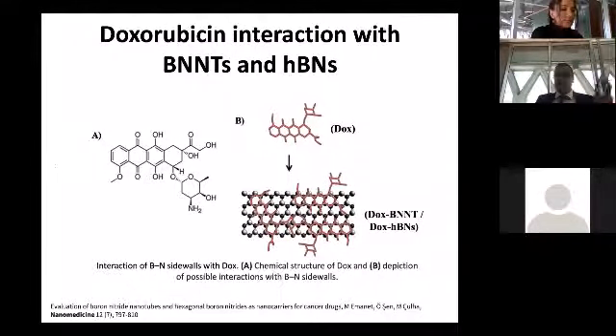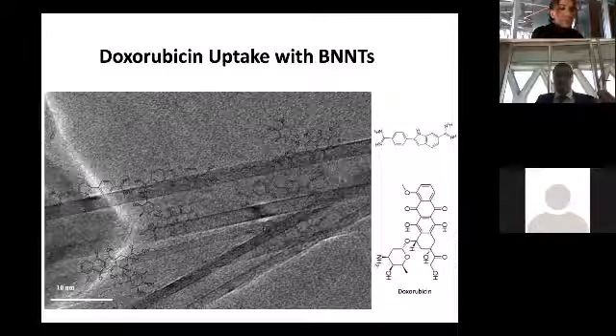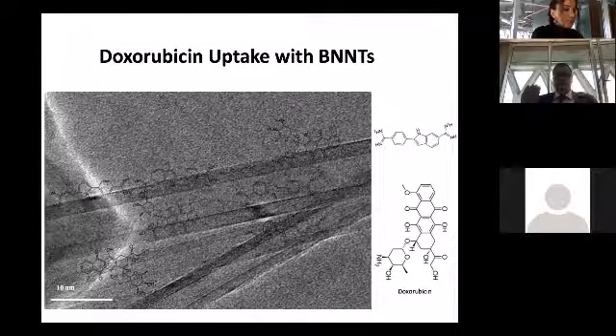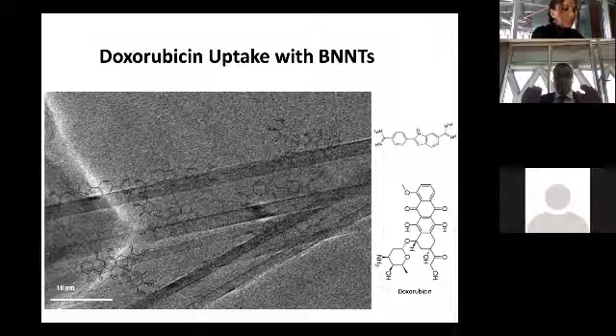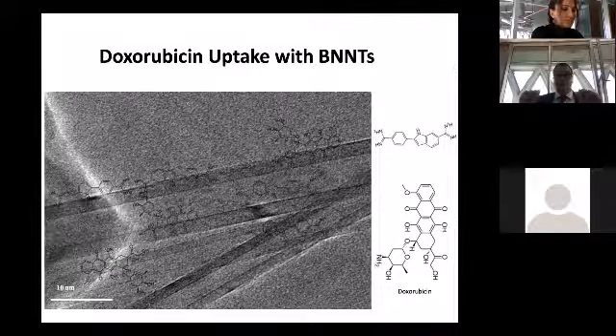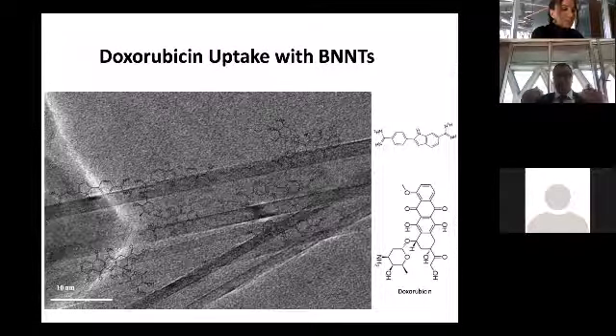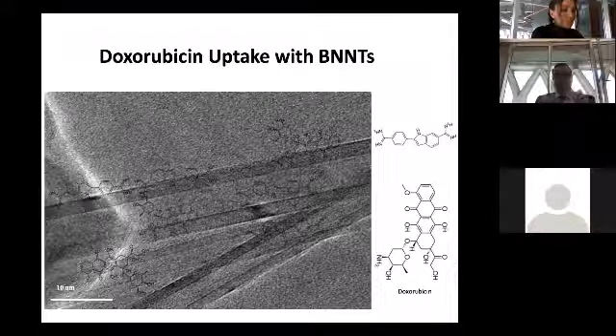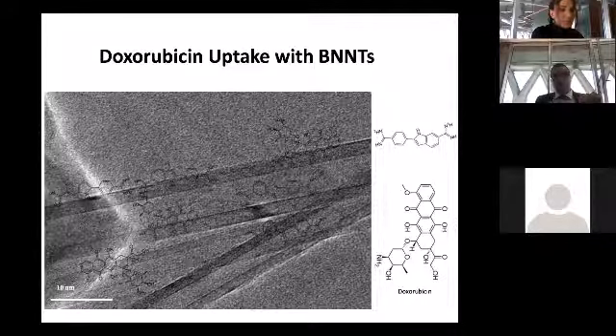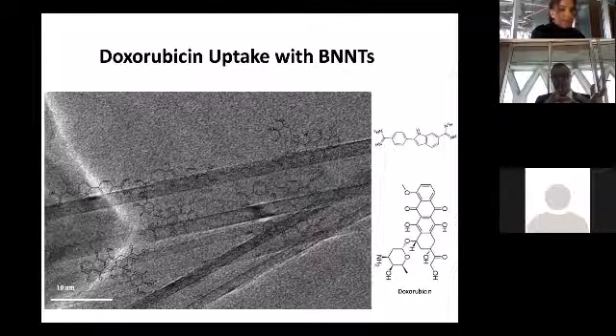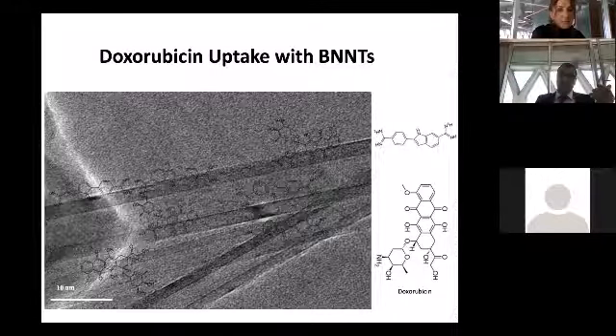And also they may interact with hydrophobic and toxic drugs. Any drugs that we tried, doxorubicin, which is commonly used in cancer therapy, this can be a good thing to carry drugs using these structures. And in a publication we compared hexagonal boron nitrides and boron nitride nanotubes, to see which one is better, and we think that these molecules can enter into the tube and also stick to the surface, and it is a good candidate for such applications.